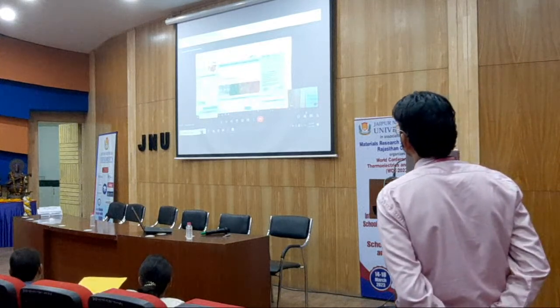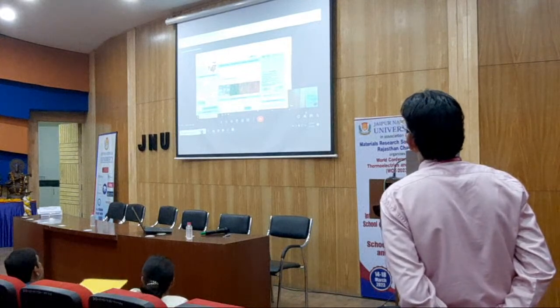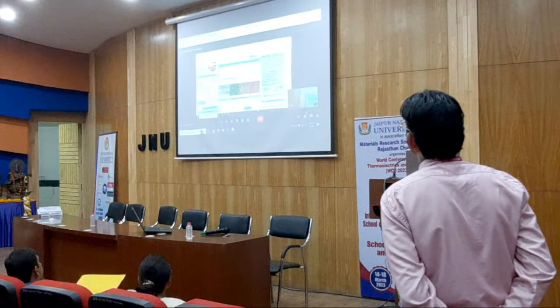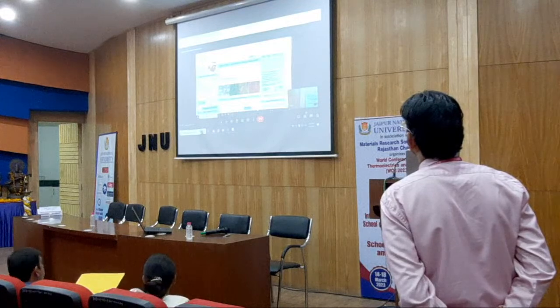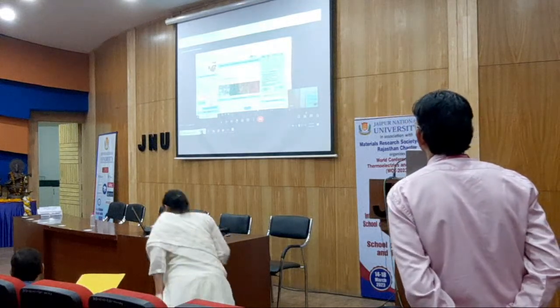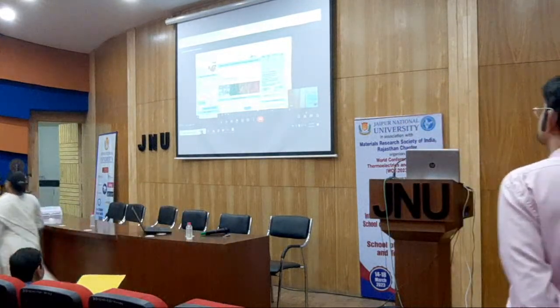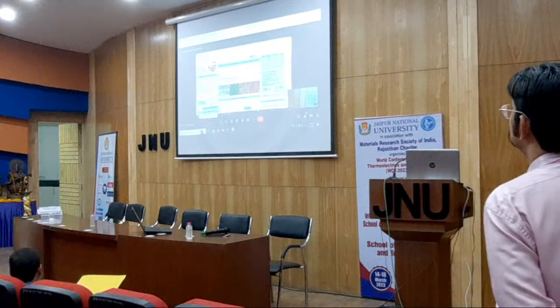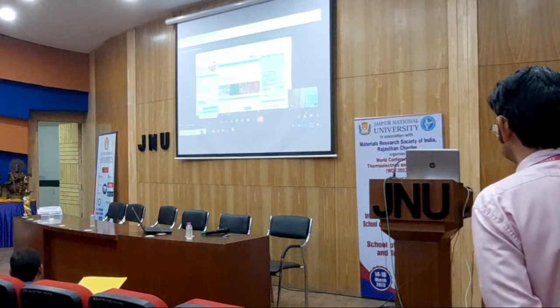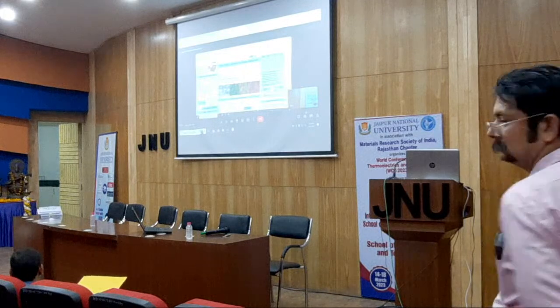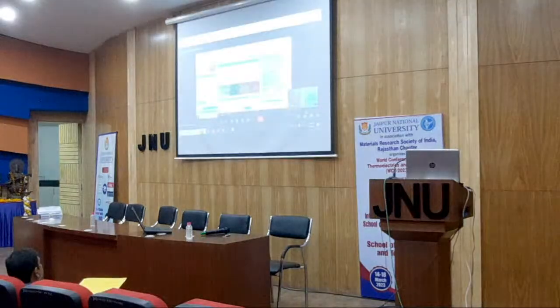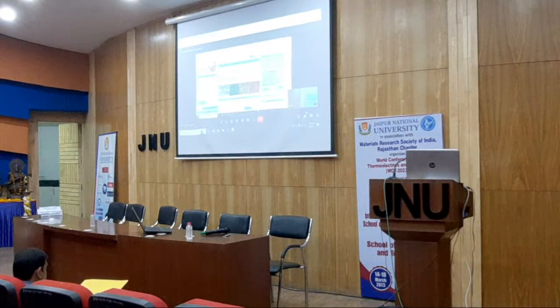But the problem is that the Seebeck coefficient and the electrical conductivity are both inversely related to the carrier concentration. With the increase in the carrier concentration, as we can see from the visual plot, the Seebeck coefficient is decreasing, but the electrical conductivity is increasing. Thus, we need an optimum carrier concentration in order to have a high figure of merit.